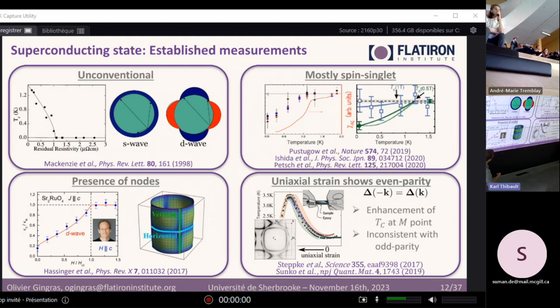So this interpretation of the result, that it comes from the Van Hove singularity, actually is because this Van Hove singularity is at the time reversal invariant point, it's at k equal minus k. This is inconsistent with odd parity pairing, and so this measurement is usually understood as a proof of the even parity nature of the superconducting state.